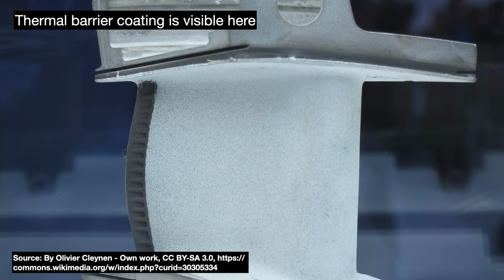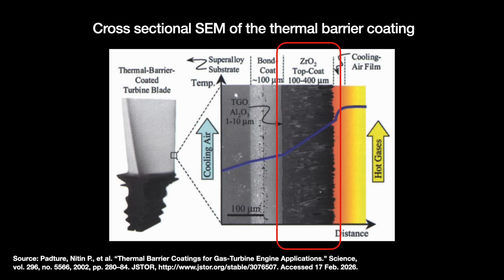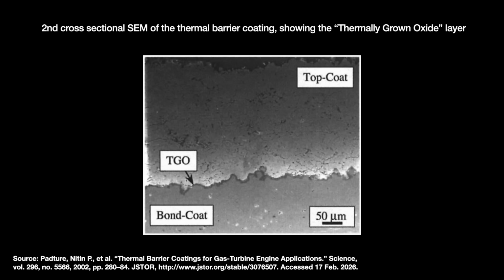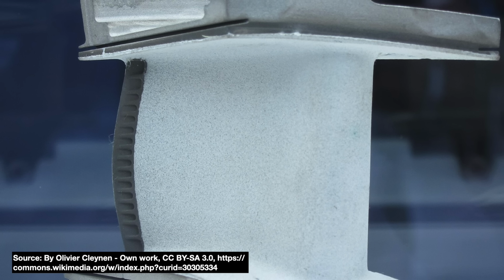They're actually made up of multiple layers. At the top, we have a ceramic topcoat layer with very low thermal conductivity. This serves as the primary insulation layer. Below that is a bond coat that adheres the top coat to the superalloy surface below, its number one job. During high temperature operations, the bond coat will help grow a third layer in between the top and bond coats, an aluminium-based thermally grown oxide layer to stabilize the adhesion as well as protect against oxidation. All of these are made from chemical compounds with enough letters to win a Scrabble game.